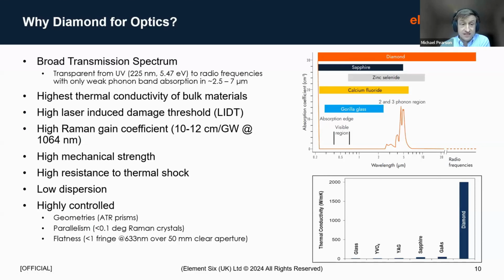The first thing really is it's an incredibly broad transmission spectrum. So diamond is pretty much transparent from its band gap at 225 nanometers all the way through to radio frequencies. It has a small amount of absorption due to phonon band absorption in the 2 to 7 micron wavelength range. But other than that, it's pretty much transparent. Depending on the grade, you might have a bit of absorption in the visible as well, but that's largely down to optically active defects, so nitrogen-containing defects. There are other impurity atoms that you can get in your diamond, but we're able to control those very well in the CVD diamond that we grow. So if you need them not to be there, we can achieve that.